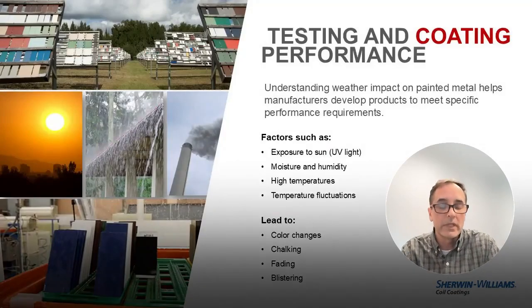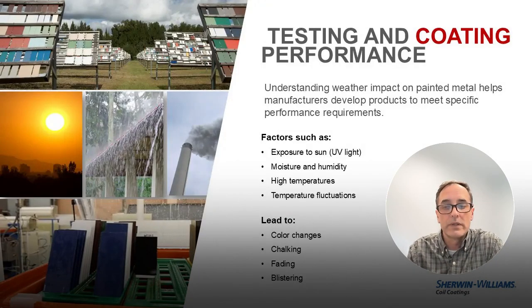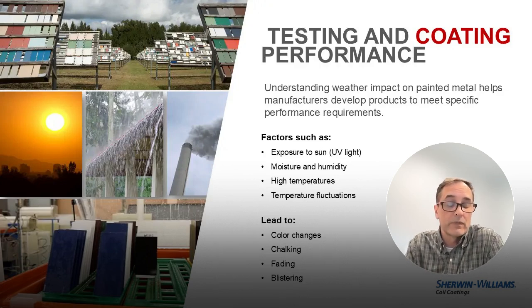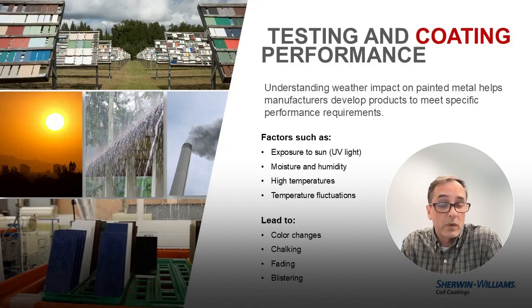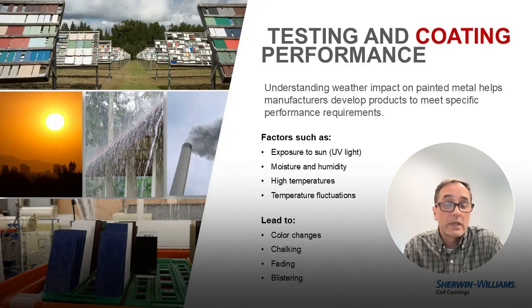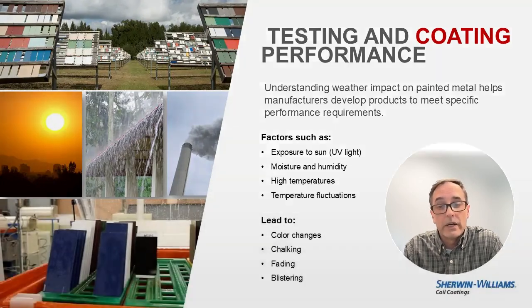Well, I would divide testing into two categories. Of course, we have the color and gloss properties, the aesthetic qualities of that coating. But as far as the durability and performance, we have tests that we can perform immediately after coating, which are very practical tests to assess the coating's hardness, its flexibility, solvent resistance, which is also an indicator of the cure response of the coating, to verify that we achieved full cure upon application.